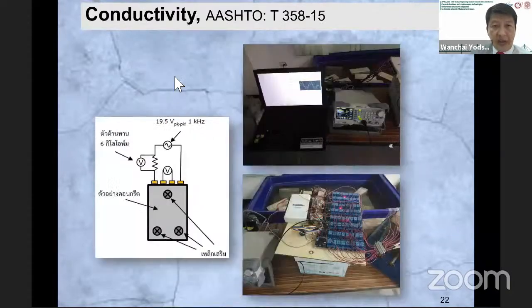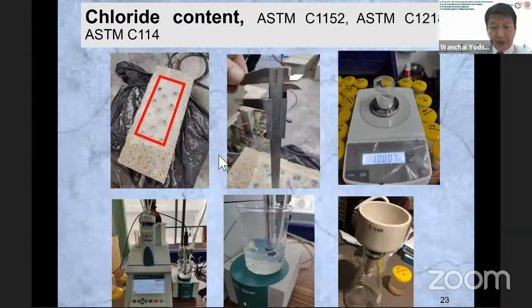And also we measure the conductivity following AASHTO T 358-15, and we have a four-probe resistivity of concrete measurement. And after finishing all the measurements, we measure the chloride content in the concrete.